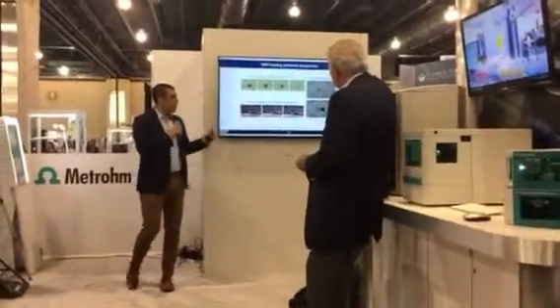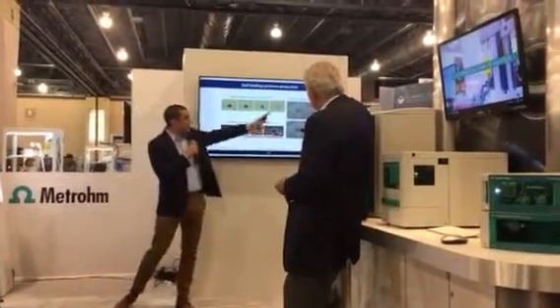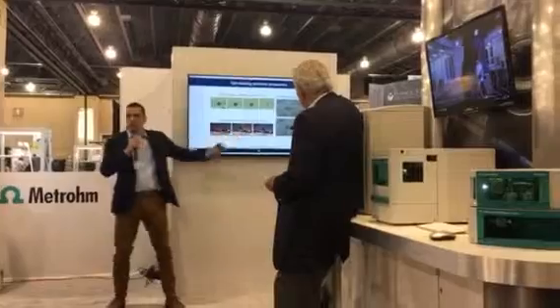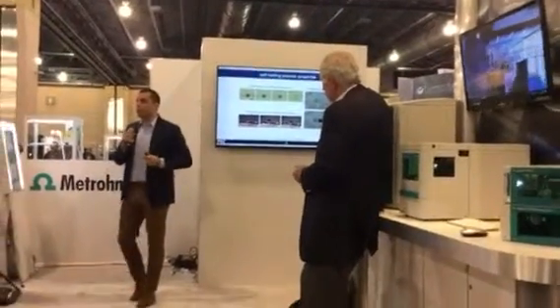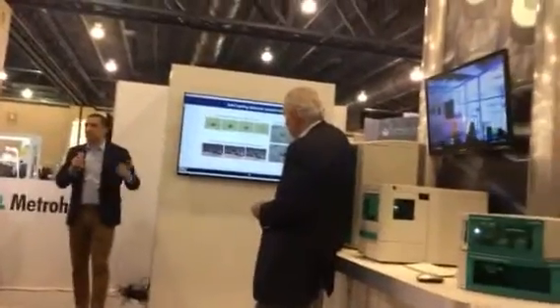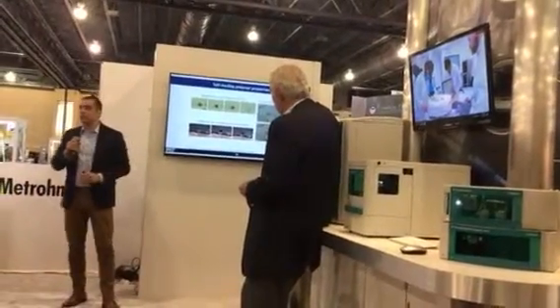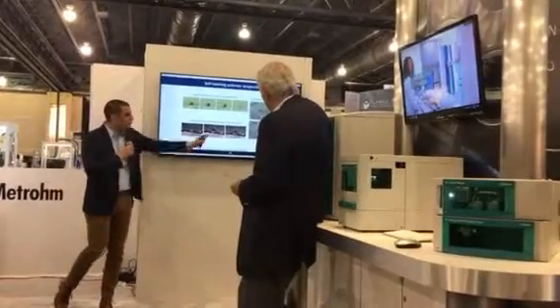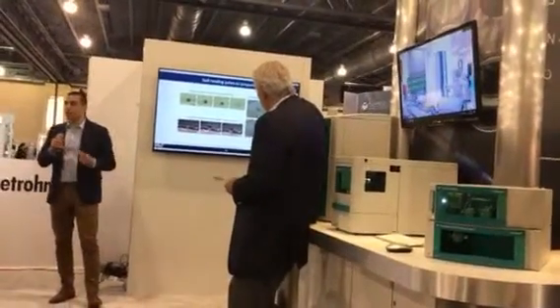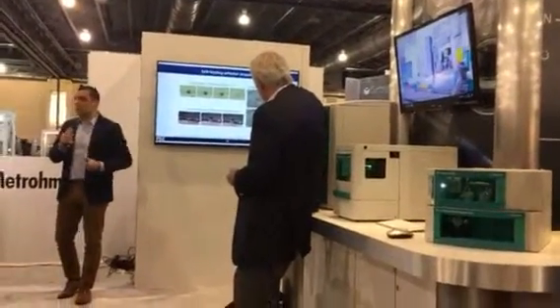And so when we coat this material on lithium metal, that's on the side here, you'll see the yellowish piece of lithium metal is coated with our polymer. The silver one is not. You leave it out in air, and very quickly, the lithium metal has reacted with the air, corroded, it's begun to decompose, even in 30 minutes. But with our polymer coating, you see it's quite stable. And so using this technology, we're able to stabilize this material and enable these batteries to cycle.